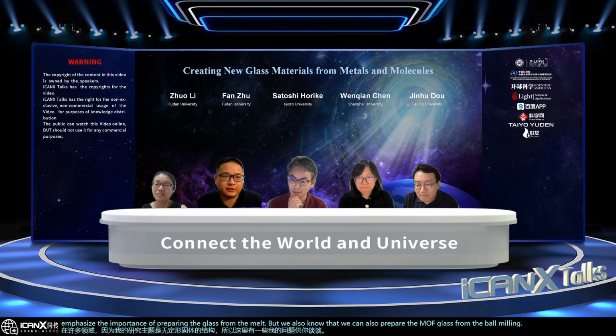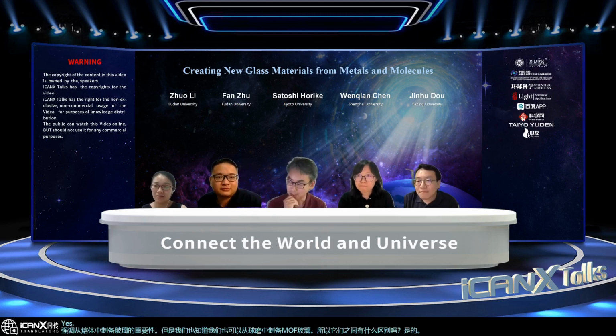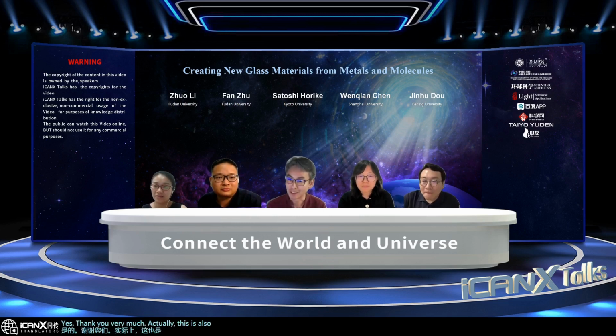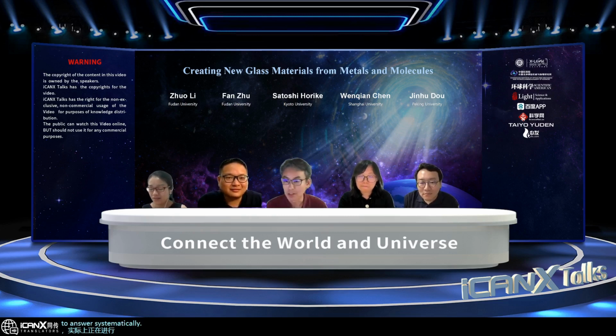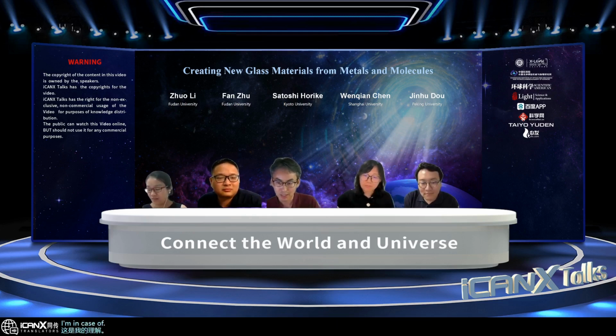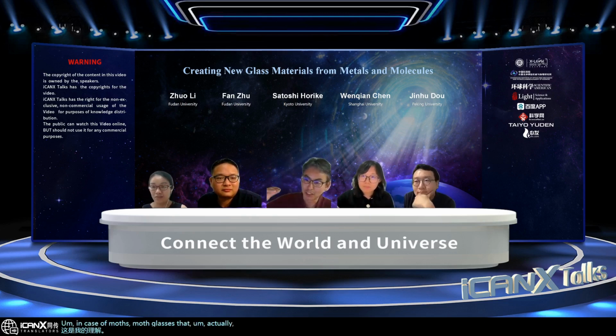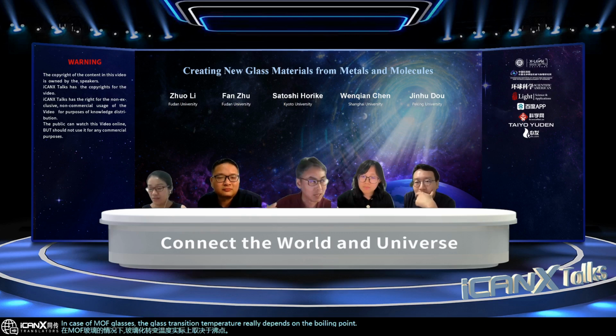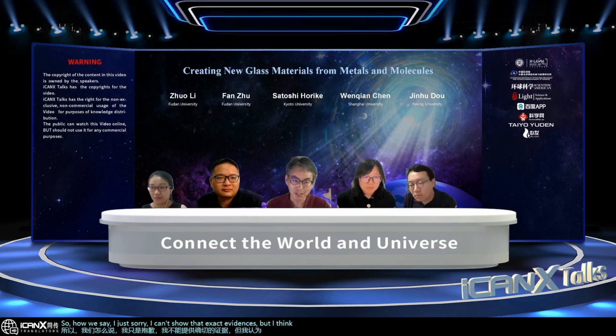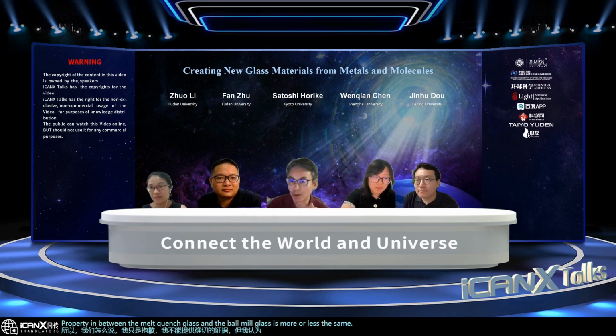Thank you very much. Actually, answering this systematically is ongoing. But when we look at chalcogenide glass, many people already agree that the structure and property of the melt-quench glass and the ball-milled glass are pretty similar. That is my understanding. In the case of MOF glasses, the glass transition temperature really depends on the ball milling time. Sorry, I can't show the exact evidence, but I think the properties of the melt-quench glass and the ball-milled glass are more or less comparable in terms of glass transition behavior and structural organization.